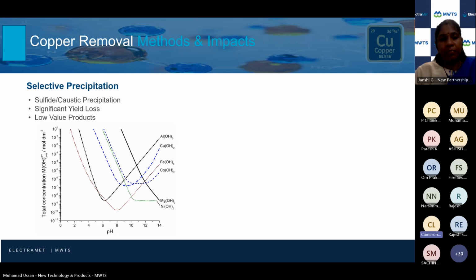So if you have to get copper out, you're looking at between pH 6 and 8 to get it all out to purity levels. But you also see that the curves for nickel and cobalt show they are also not soluble. So it's not selective. It's going to get all those metals out. So if you go forward one step, this is looking at sulfide precipitation. Can you advance one slide, please?